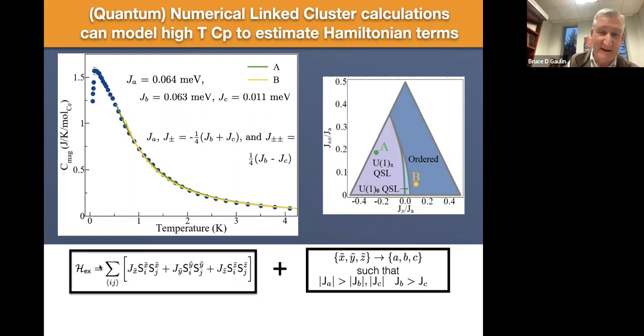And basically, because these measurements are on the heat capacity in zero field, the Hamiltonian that is modeled is not exactly this XYZ Hamiltonian, but it's related to it. It's the XYZ Hamiltonian where the 3 exchange constants are ordered in the order of their magnitude. So they don't model JX, JY, JZ. They model JA, JB, and JC, where JA is the strongest one, JB is the next strongest, and JC is the weakest. Okay, and so the phase diagram that they consider is this phase diagram that's shown over here.